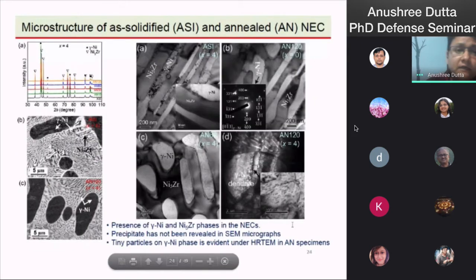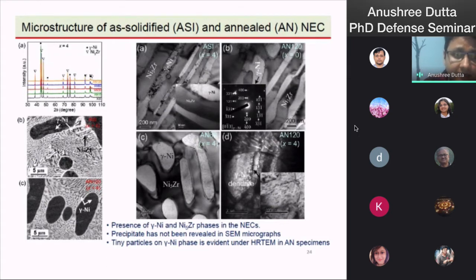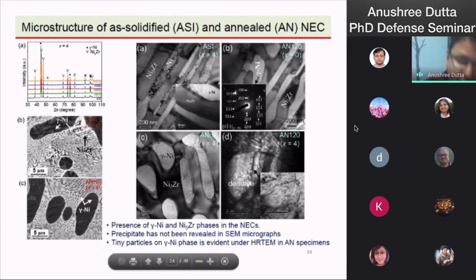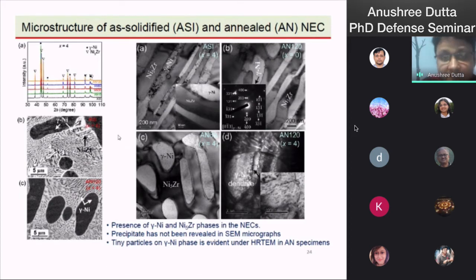The microstructure analysis, SEM investigation, shows that there is no change of microstructure after annealing. This is the as-solidified and annealed sample SEM images. No change of microstructure and no coarsening and no spheroidization occurs after annealing. Whereas the HRTEM high resolution transmission electron microscopy image indicates the evolution of small precipitates after annealing for up to 120 hour and 160 hour annealing period. After 160 hour annealing, no evolution of precipitates is observed in binary alloys.